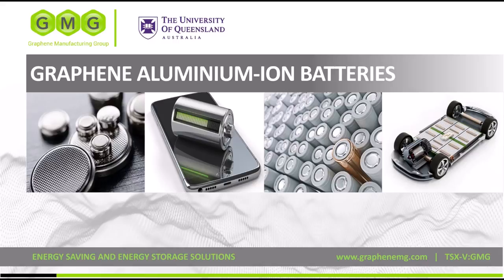The graphene is manufactured by a low-cost process developed by GMG. Natural gas is used as the feedstock — add a bit of electricity and GMG's special process — and you produce graphene and hydrogen. One gigajoule yields approximately 15 kilograms of graphene. To give an idea of what this looks like, a 9-kilogram LPG tank we use on our barbecue is about 417 megajoules, which would yield about 6.2 kilograms of graphene.